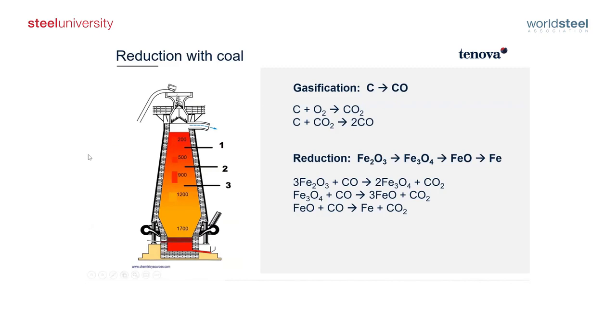In the blast furnaces, the iron ore is reduced from iron oxide to metallic iron by means of a reaction that's based on carbon. The coking coal charged into the furnace together with the burden is partially burnt and transformed into carbon monoxide. And inside the shaft of the blast furnace, the carbon monoxide operates the reduction of the iron ore into metallic iron, at the same time melting the gangue into slag. The result of this process is liquid hot metal with high percentages of carbon, 3.5% and upwards, and the byproduct of the production of metallic iron and slag is, of course, carbon dioxide.